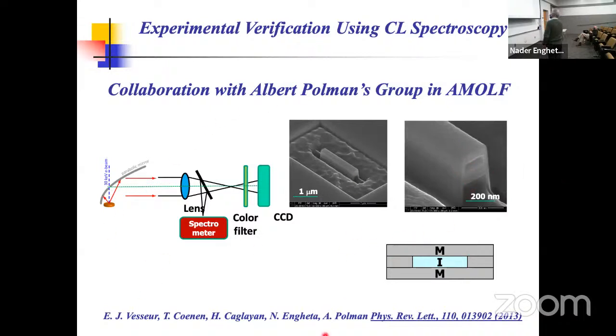Now, Albert Polman has cathodoluminescence spectroscopic imaging in his lab. What is that? An electron beam comes down, at about 30 keV, and this electron beam hits the sample. At the location that it hits the sample, it can emit photons by transition radiation. When the electron beam hits the sample, it penetrates through the silver, goes into the dielectric of the waveguide, and at that point emits. So essentially it becomes like a little optical antenna at the location that you want. The cross section of that beam has a diameter of about 4 nanometers.